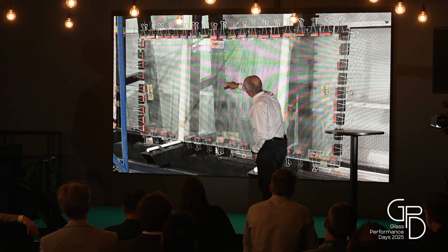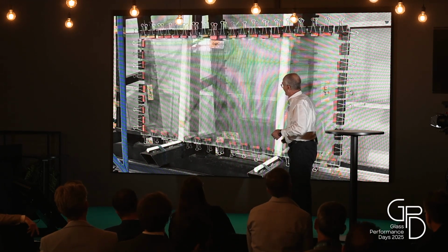I don't know if some of you saw the presentation on what clipping does to laminates. We did two laminates, and we clipped only one short side and one long side. Here there are two laminates on top of each other. I wanted to induce distortion, but we used stiff PVB, and we should have used another material to get a little bit more. So overall, the glass was not that bad. But anyway, we set it up.